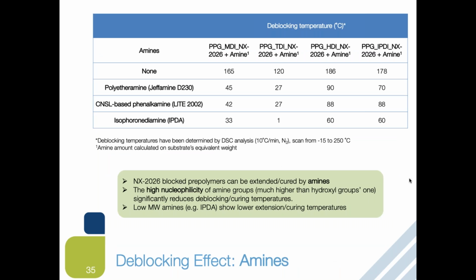So amine, once again, can be used as a deblocking agent, and this is a powerful one. Once again, the same type of prepolymer with a different isocyanate and blocked with the NX2026, and then we blend them with amine, and the amount of amine will be based on the equivalent weight of your system. Here, once again, just to repeat, without anything else, deblocking temperature is very high.